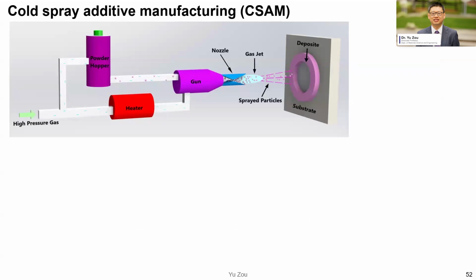Another method I want to mention is cold spray. Cold spray is based on high pressure gas. The high pressure gas will accelerate the metal powder particles to supersonic speed, and then layer by layer, they can form a coating. Here I want to show you a few parts. So you can see there's a difference in thickness. This is aluminum powder particles deposited on a substrate. This is copper particles deposited on a steel substrate.